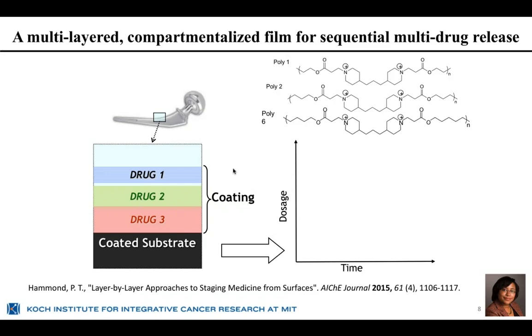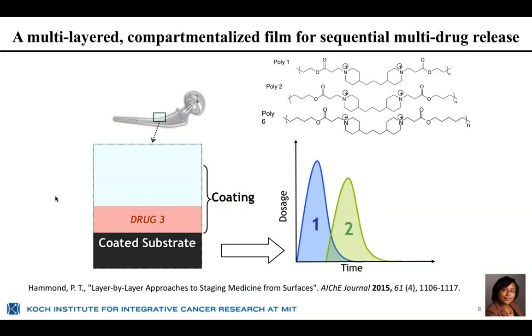Finally, if we're able to introduce very nice diffusion barriers between the layers, then we can get not only unique release profiles, but phased release in which the drugs come out at different times. And these can be very advantageous if we want to have a more complex release profile in which we release, for example, something like an antibiotic followed by a growth factor. We've been doing a lot of work, in fact, looking at these systems for bone regeneration.